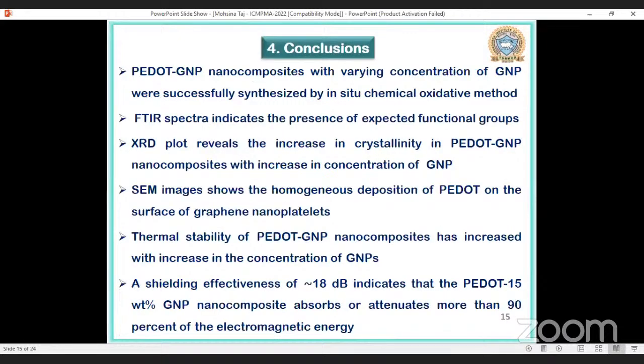Generally, the grading values of electromagnetic shielding effectiveness are tabulated here. If the shielding effectiveness is greater than 10 dB, the material can attenuate more than 90% of the incident electromagnetic radiation. And we have obtained around 17.6, that is around 18 dB of shielding effectiveness for the material that is PEDOT with the 15% of graphene nanoplatelets. This indicates that the material can attenuate more than 90% of the incident electromagnetic radiation.